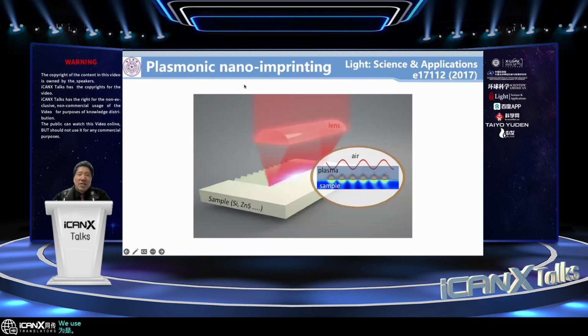we use plasmonic nanoprinting technology to create nanostructures also with very high efficiency. We know if we couple light into the metal surface, then we can launch the surface plasmon. Then the surface plasmon wavelength will be much shorter than the laser wavelength. For metal, certainly there's no problem, we have a very high density of free electrons. But if we want to do fabrication using femtosecond laser on other materials, how do we achieve such a high density of free electrons?